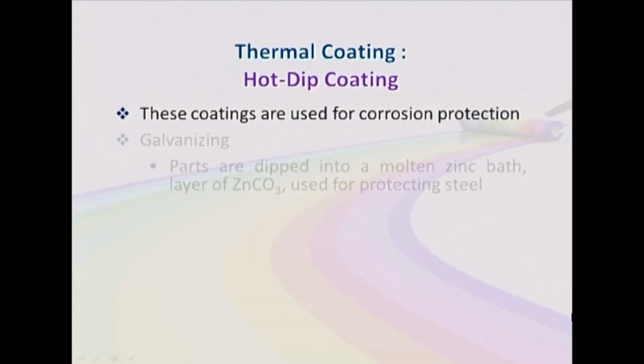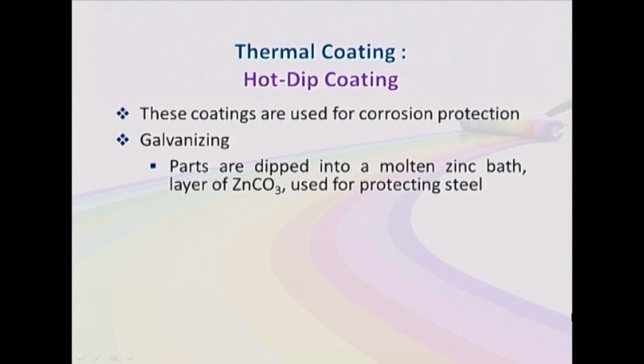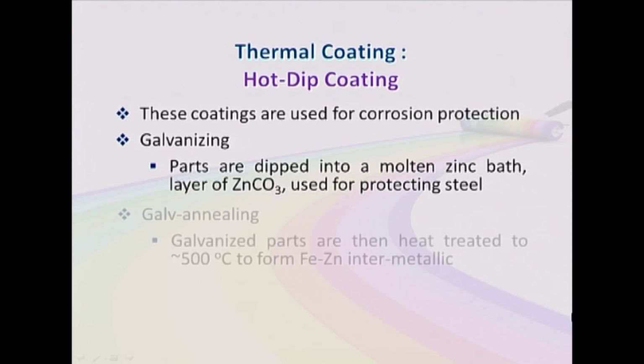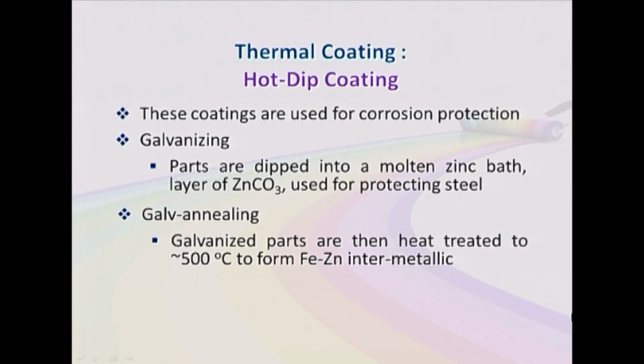Next type of thermal coating is by hot dip method. These coatings are also used for corrosion protection. First of all, galvanizing. Parts of the substrate are dipped into a molten zinc bath. A layer of zinc carbonate will be formed, and this type of coating is used for protecting steel. Galvannealing. Galvanized parts are then heat treated to around 500 degrees Celsius, so that an iron zinc intermetallic state is formed.